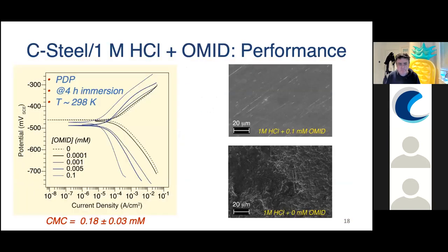So let me first of all demonstrate something about the performance of this corrosion inhibitor. In this case, it's carbon steel, and we're in one molar hydrochloric acid. We've immersed a sample for 4 hours. We usually do 4-hour immersion experiments because that's convenient for our work. And that gives you enough time for the system to come to steady state, so the open circuit potential is stable. And the temperature is around room temperature here.